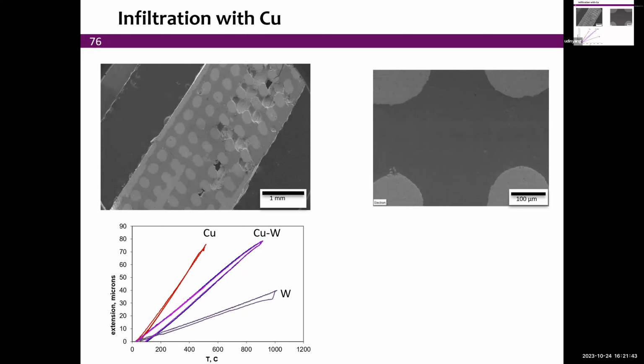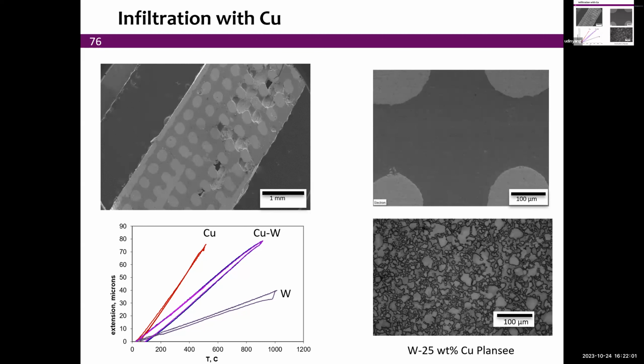It's really interesting because in many cases, you would like to match the thermal expansion of material, especially in cooling situations, or if there's big swings of temperature, otherwise you start delaminating. And both copper and tungsten have very good thermal conductivity, so you end up with excellent thermal conductivity. In fact, commercially, this is what you get, a tungsten 25% copper composite, but where the folks at Plansee just infiltrate tungsten particles with copper, which is very different from this.